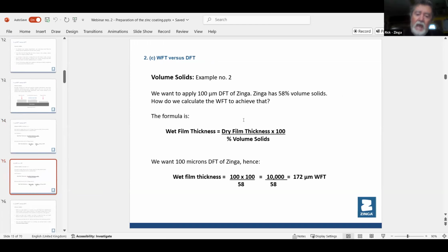So this is to show you here, as I was saying earlier, that's how you get it. If you want 100 microns of thickness, same thing. You take the 100, you multiply it by 100, it's 10,000, and you divide it by the 58% volume solid, 172. So if you get 165 or you get 178 wet, leave it. That's fine. It'll dry so close to your required dry film thickness. So don't muck around putting extra coats, whatever. If it's close enough, just leave it. It's fine. You still get your durability.